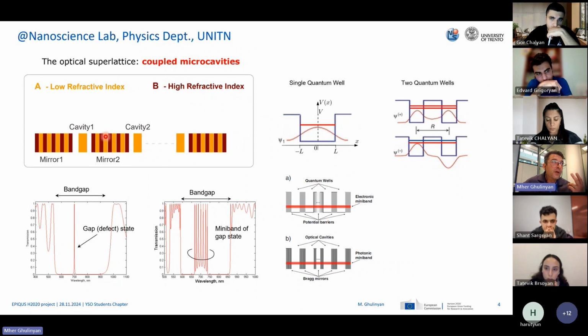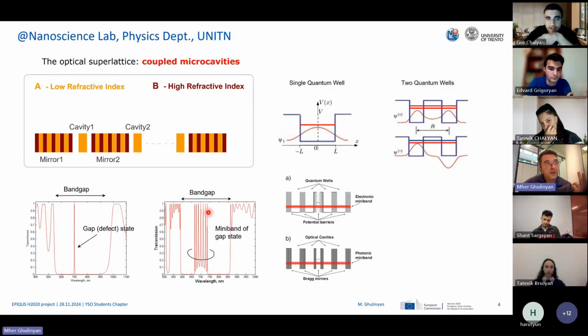When this mirror is not ideal, these two cavities start to communicate, let's say. So they couple exactly like here. Because of this coupling, the single resonance, which is common for both, is splitting into two resonances. If you put 7 cavities, your single resonance, which is equal for all of them, you will see a spectrum of 7 separate peaks. I don't know if I was clear or not.